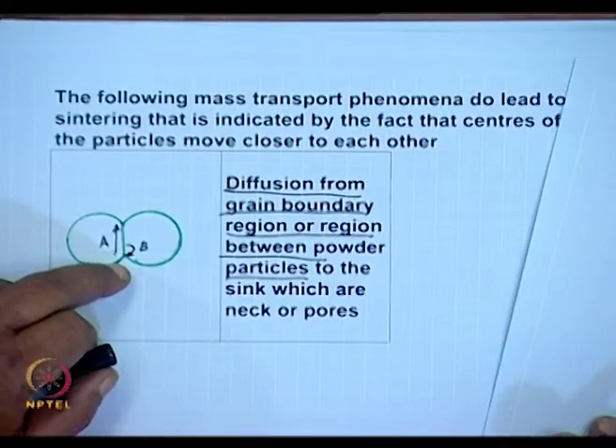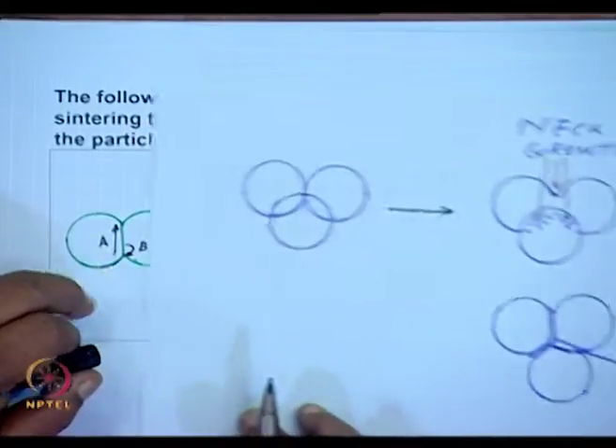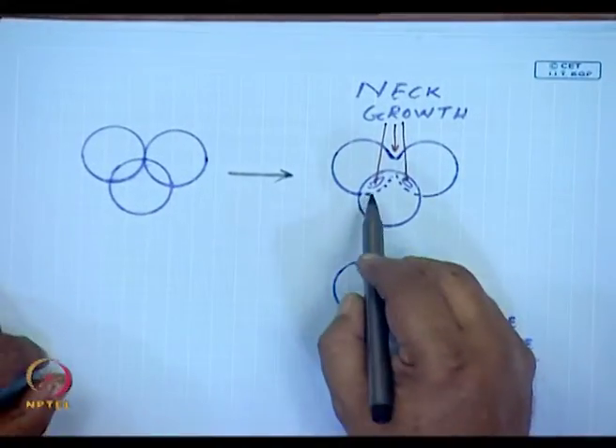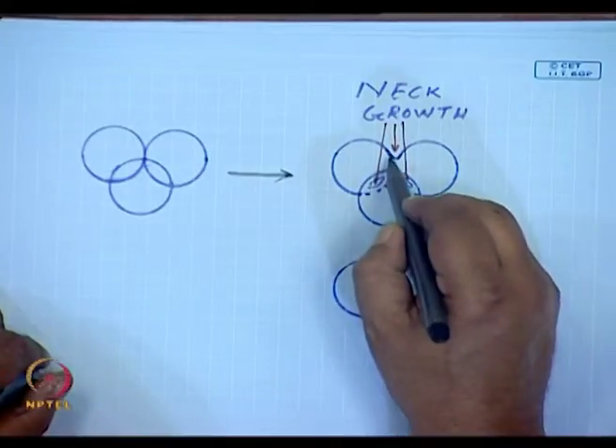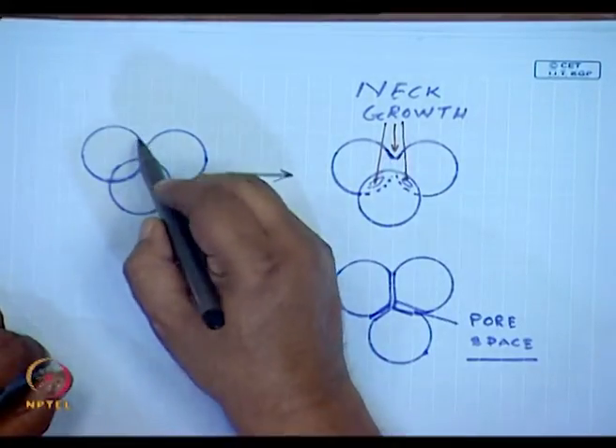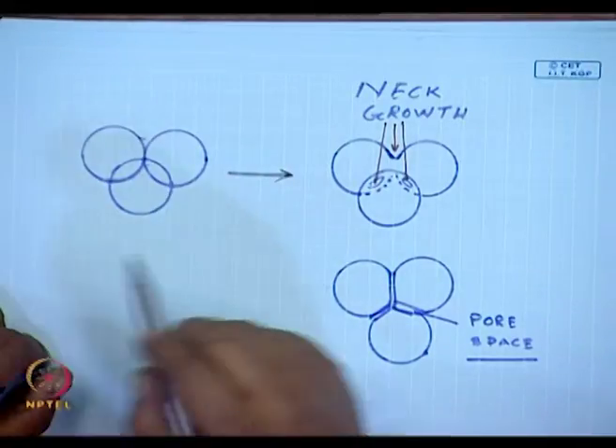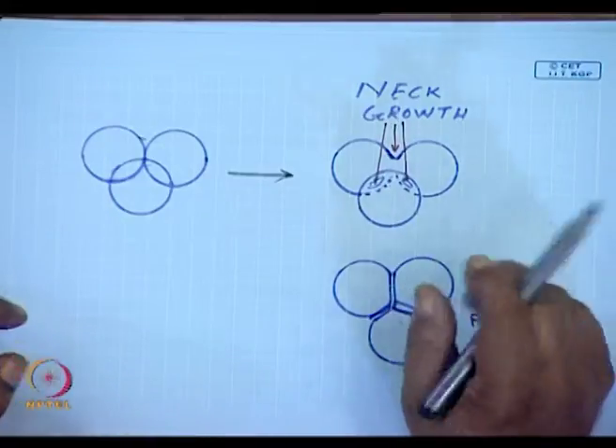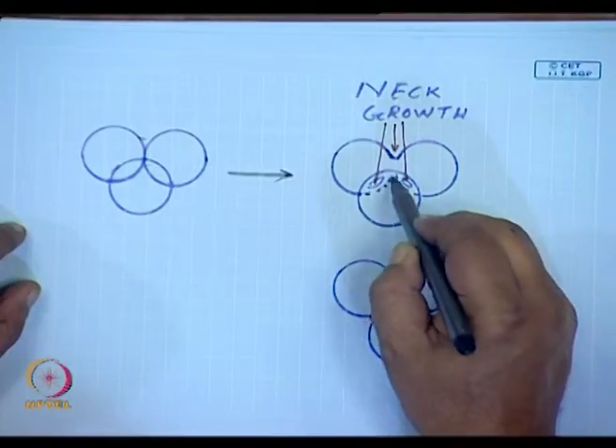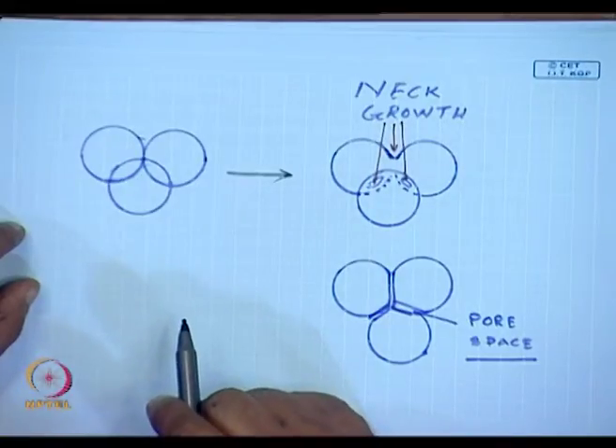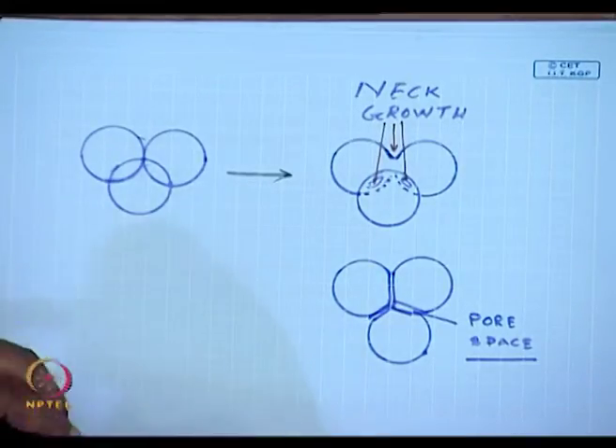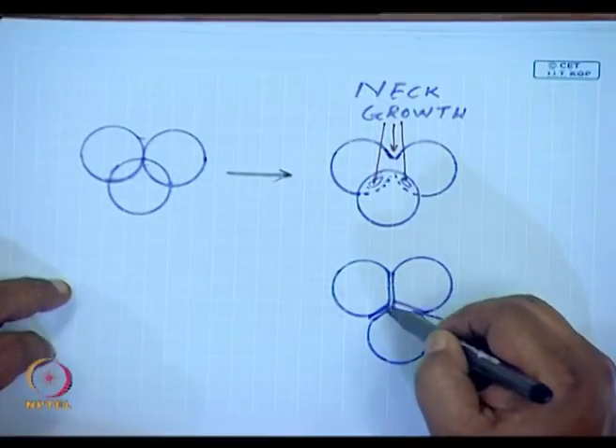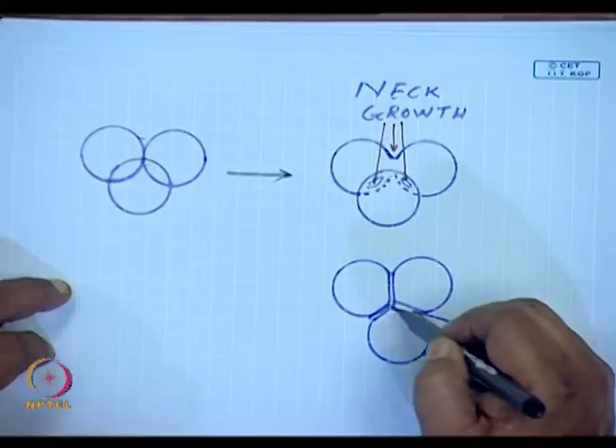First of all, through these mechanisms, there is diffusion from the grain boundary or the region between the powder particles. What happens is neck growth starts happening. A neck forms over here - you can imagine a ball with a flattened surface. As more and more diffusion occurs, these surfaces tend to flatten out, in this fashion.